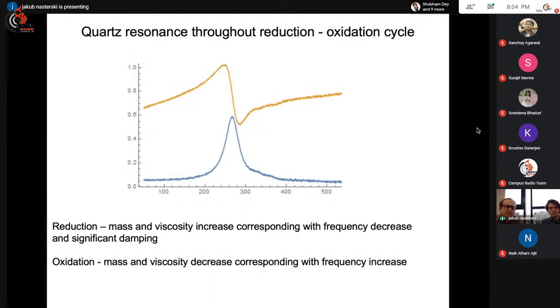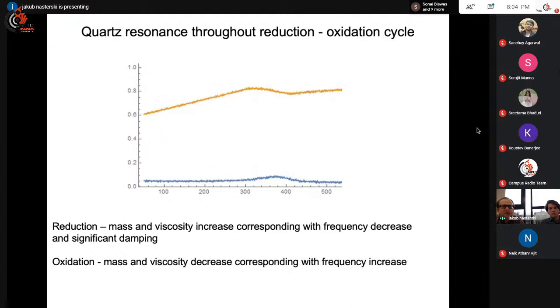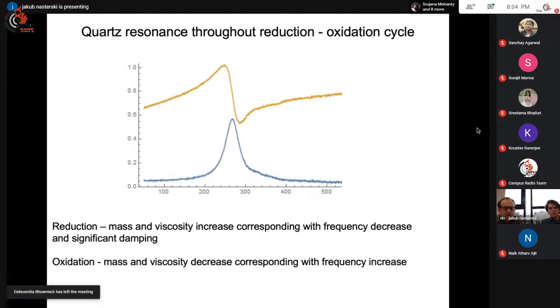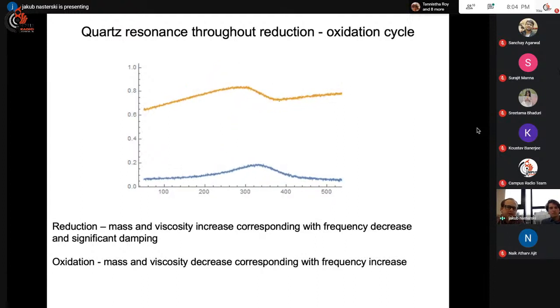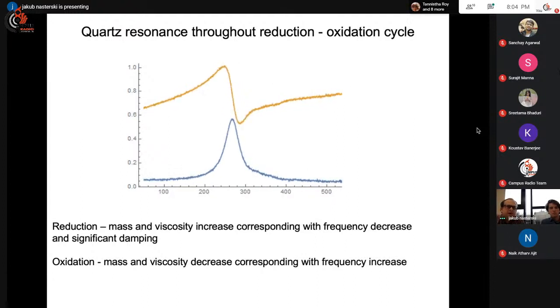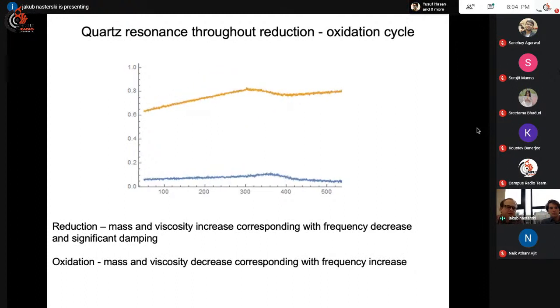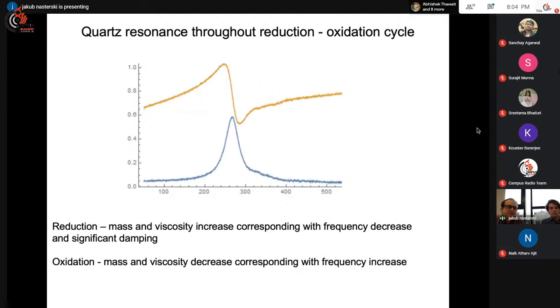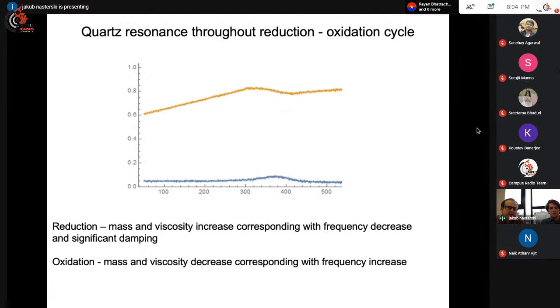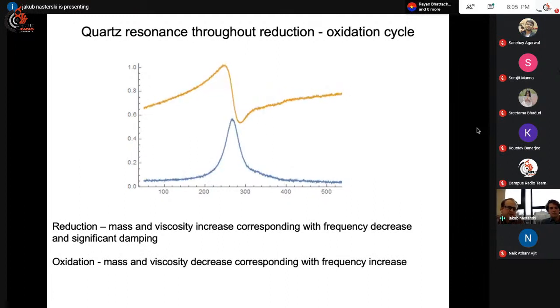So what exactly happens to the crystal when you do the what is called the reduction oxidation cycle? You can see that this is the oxidation state, and now we're going into reduction. So again, this is an oxidation, and peaks are sharp because there is no load on the crystal. During the reduction cycle, metal deposits on the crystal surface, viscosity increases, so there is a very significant damping effect, which Jakub already mentioned, and there is hardly any frequency reading. Again, going back to the empty crystal.